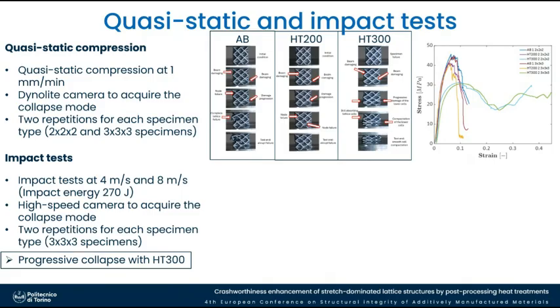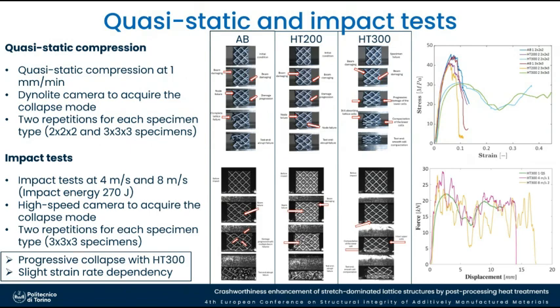Then we move to the impact test. We performed impact tests at 4 meters per second and 8 meters per second, basically 14 and 28, more or less, kilometers per hour. We recorded the collapse through a high-speed camera, and we did the test only on the 3x3 specimens. And what we observed was that, again, the 300 degrees